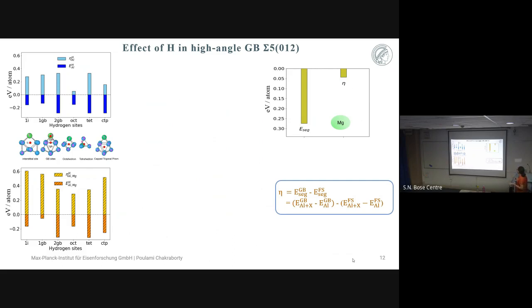This is very important. Why is this important? Because this will definitely give us knowledge or the probability of whether this whole system will be driven to free surface formation. However, there is one thing that is missing in this parameter. This parameter doesn't give you the energy gap, the energy barrier that is needed to cross from the grain boundary to the free surface. That means, if you want to go to the free surface, what is the energy barrier that you need to cross? That is not given here, but it definitely gives you the tendency, or which surface makes you happy. So therefore,